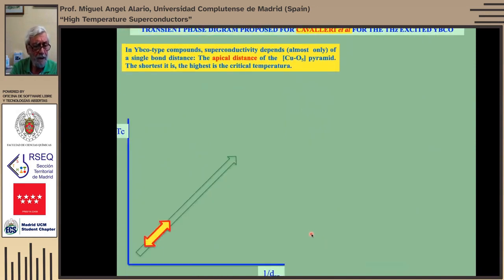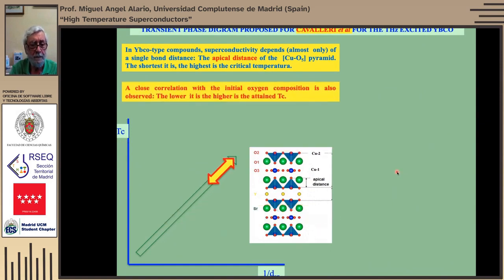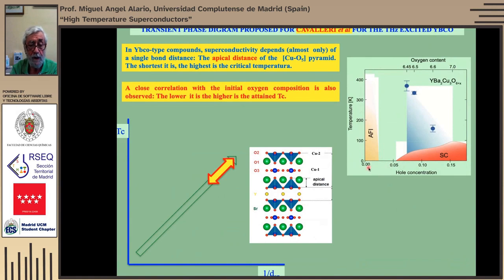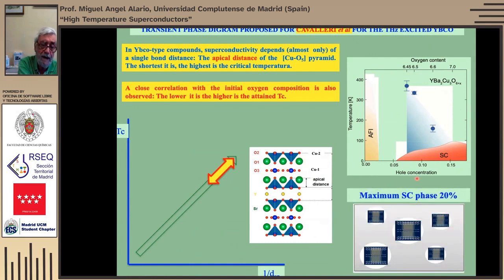We get superconductivity, but in a very brief time. Now, the phase diagram that they have done with many studies, the people of Cavalieri, is that you have the hole concentration that depends on the oxygen content, and this is the critical temperature, and thanks to these pulses, you can actually, depending on the oxygen content of the stuff, get a TC, which is here 150, 350, so quite higher than room temperature. But as I say, and it's very important, it is very brief, and also you cannot get much phase superconductivity. If we suppose that this is the material, we only have about 10% of regions which became superconducting and back to non-superconducting. So every pulse you get it.